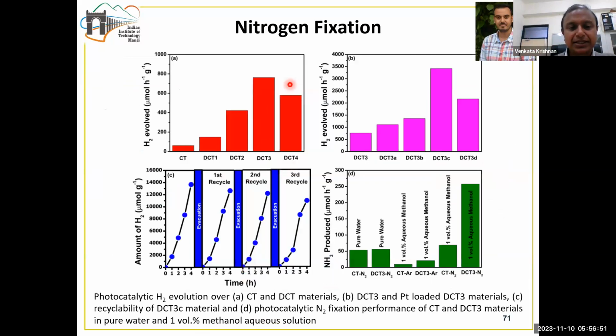Then we utilized this catalyst first for hydrogen evolution, because the same catalyst can be used for both hydrogen evolution and nitrogen fixation. Every experiment here is done under direct sunlight irradiation. The hydrogen evolved from water was made to combine with the nitrogen, and finally we were able to get ammonia. We are also examining the recyclability of this reaction.